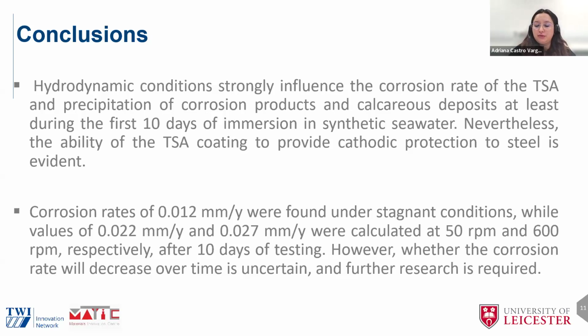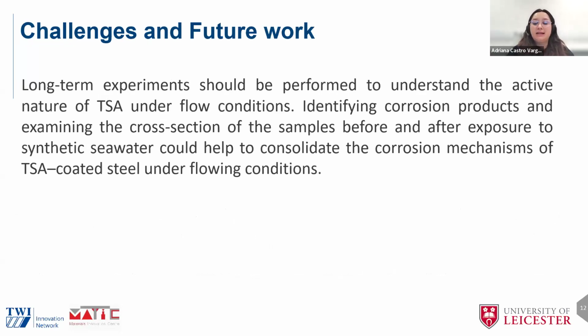However, whether the corrosion rate will decrease over time, and whether these layers are more stable over time, is not clear with these short experiments. And of course, more research is required. So basically, as a challenge and future work, it's important to also identify the corrosion products and do a deep examination of the cross-section before and after exposure, in order to consolidate the corrosion mechanism in a better way, because we have mass transfer in the system. But it gives us a good idea about the corrosion rate, especially in the first days of immersion.